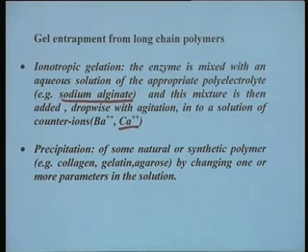But sodium alginate is a water soluble polymer, and it can be mixed with enzyme solution, and then you extrude this mixture through a fine syringe into a calcium chloride solution and agitate it, and by the exchange of ions, the sodium gets exchanged with the calcium, and you get water insoluble beads. One of the major advantages of this method is that in the case of previous methods you get a block of gel, and the gel block has to be mechanically dispersed into a particular shape for use in the reactor. Here you can prepare the immobilized enzyme preparation almost in bead form, so that it can be directly used.